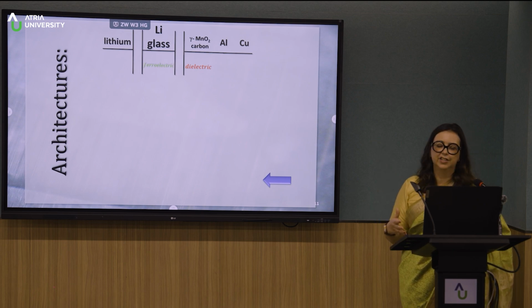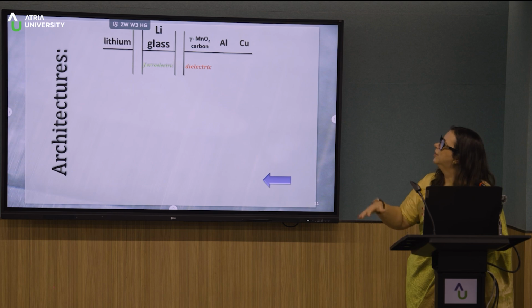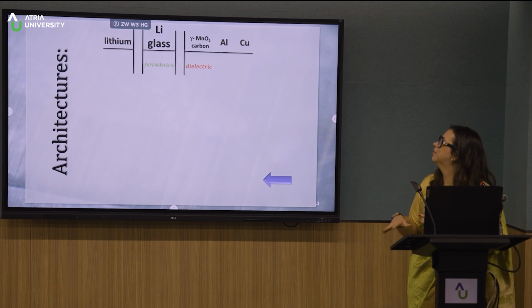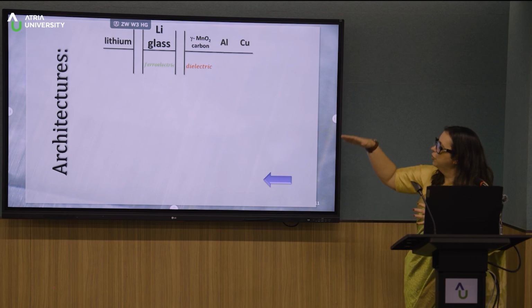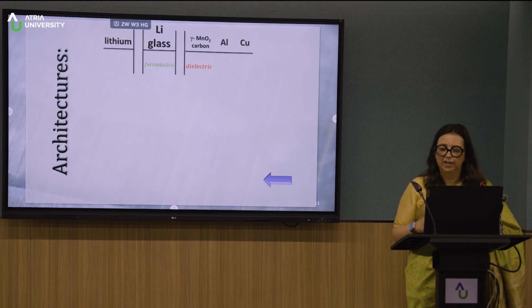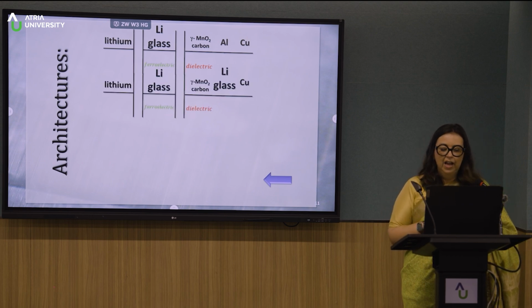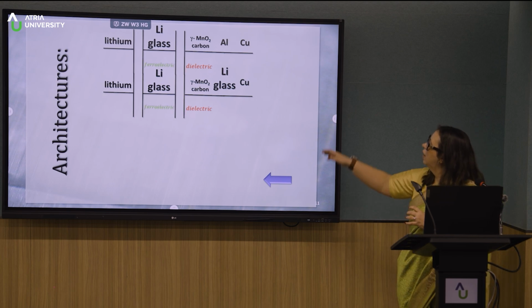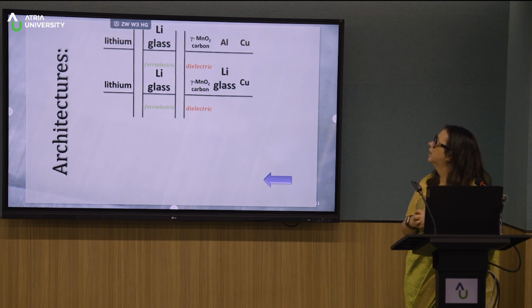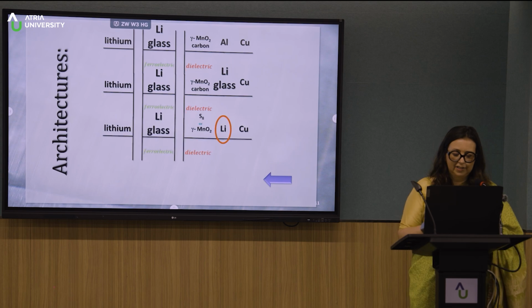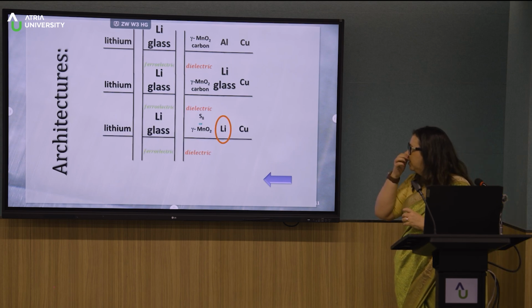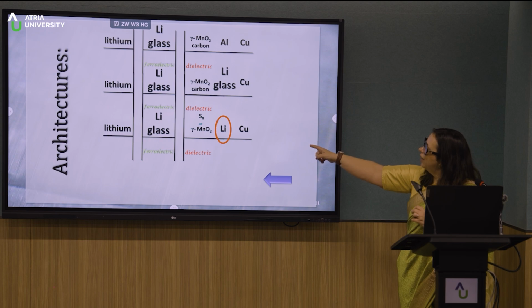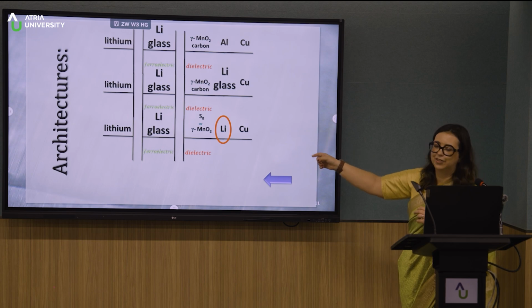So the copper has the chemical potential down at 0.5 if you are in the SHE scale. But if you are in the absolute scale, the work function of copper is more or less 5. So you bring the chemical potential down as you want in the cathode. And here we also made some cells with lithium glass on the cathode as usual. But what is not usual is that we were able to make some cells where we put lithium on the positive electrode, so on the cathode side.